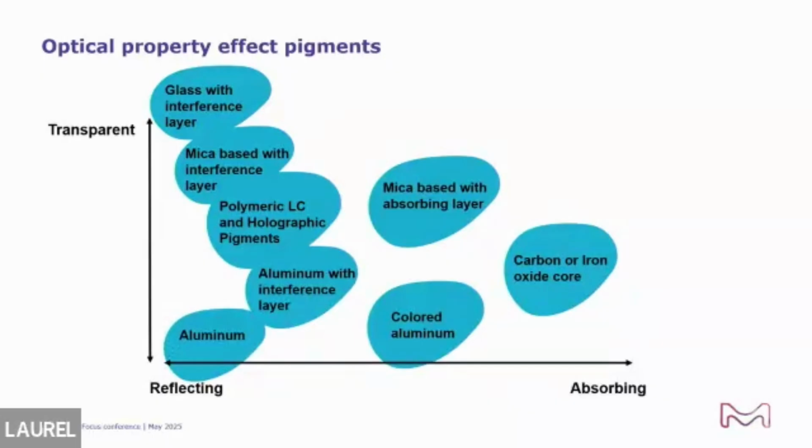Depends on what you want. So you can see if it's an iron oxide coated substrate, it will have better hiding than titanium dioxide coated, because iron oxide has an absorption color, it's a reddish color. So your red and your orange always have better hiding than your interference blue or your interference green. So that's just how it plays.